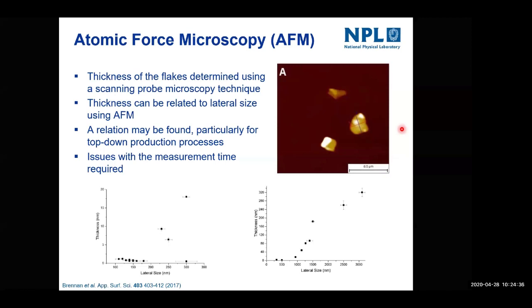So one of the ways of getting around that is to look at correlations of lateral size versus thickness. Now, not all materials have a correlation between lateral size and thickness, but most of them do, because of the way that they're produced in a top-down way. So that means you can get this relationship between thickness and lateral size. At the same time, there might not be a correlation, so it does go back to looking at hundreds of particles to get a statistically relevant sample.